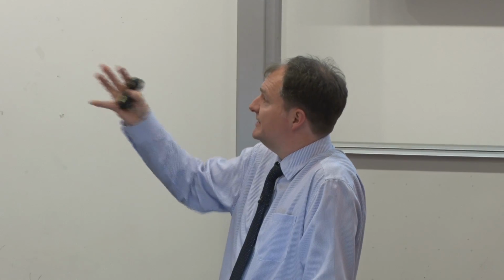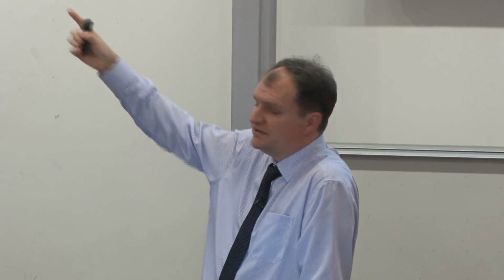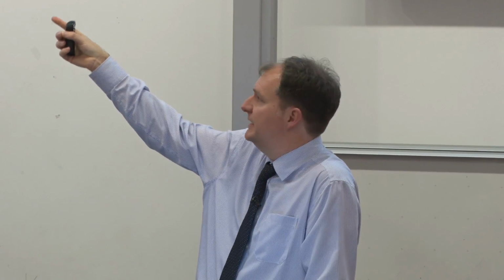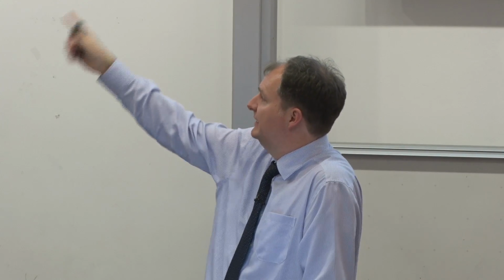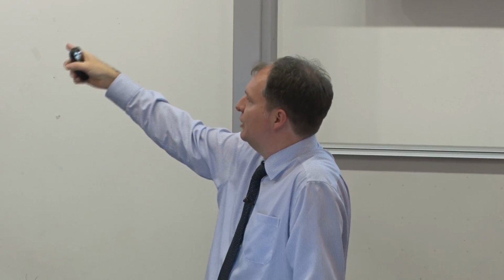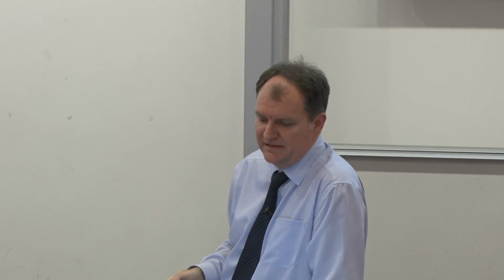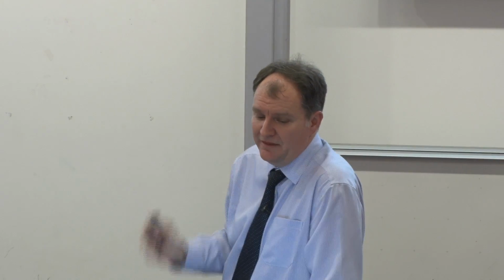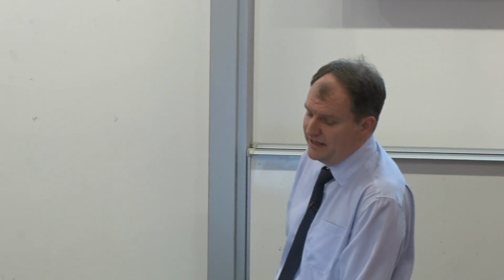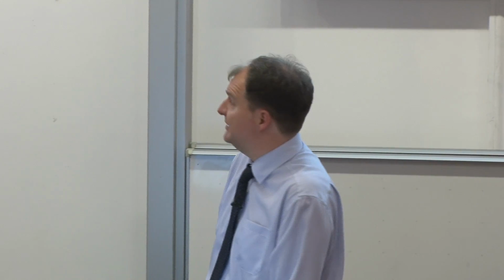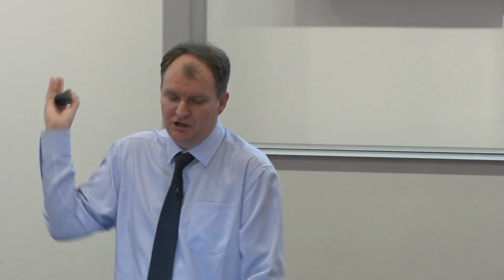We also carried out simulations at the scale of the individual particles. So this is simulations, but starting with one of these micro-CT images. So we were actually predicting the leaching of these rocks, how the grains are disappearing, and then we could compare them with the real experimental values. And these were calibrated up to 35 days and then predict the long-term behavior.